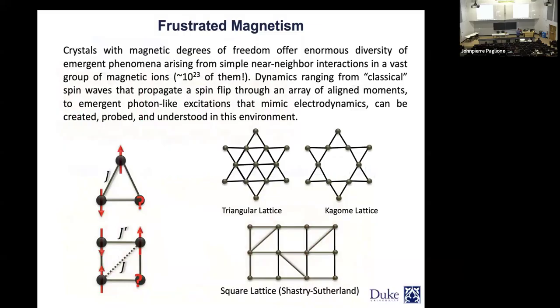So, for example, your motif is going to be a triangle. I'm sure you have seen this 100 times. If you call the exchange interactions between these sides antiferromagnetic, so my J is going to be an antiferromagnetic interaction, and what is also important is that if you have an Ising type interaction, your spins won't be able to rotate around too much, but they would be able to point up and down with respect to each other.